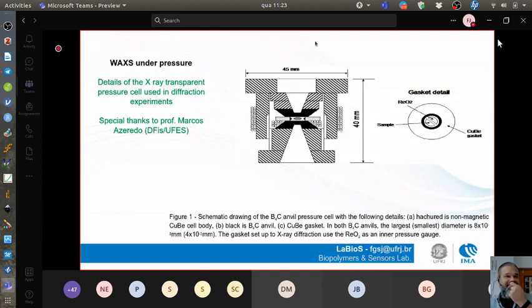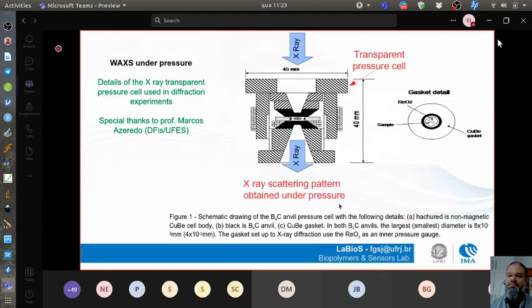Okay, and to do this, the WAXS measurements under pressure were only possible because of this professor from my former university, Professor Marcos de Azeredo. Professor Marcos de Azeredo prepared this amazing pressure cell, and this pressure cell is invisible to the X-rays. So here in the middle of the cell, we put our sample. All this cell was compressed, and then we passed X-rays through it. Okay.